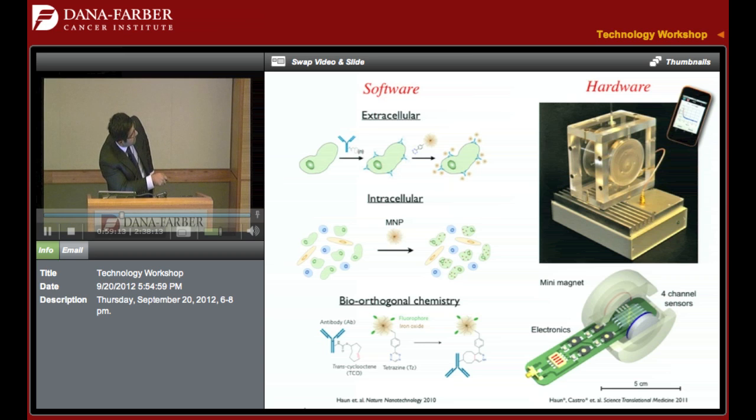We have our antibody of interest, either to extracellular or intracellular targets, followed by a second step of labeling or decorating with our magnetic nanoparticles, our cross-linked iron oxides in particular. We try to load as many nanoparticles as we can onto our antibodies before encountering steric hindrance. This is how we achieve high signal to noise, which is the currency of imaging and sensing technologies.